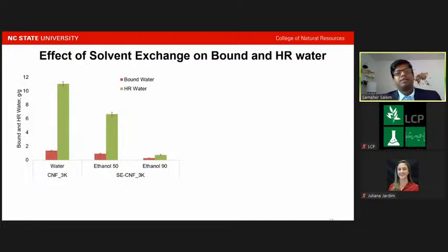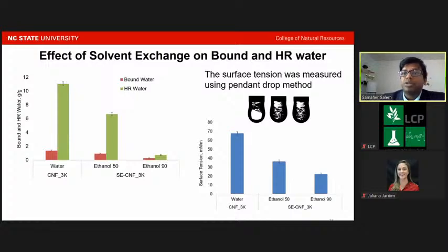Now, when we tried to find out how the solvent exchange method increases the reactivity, we measured the bound water and the hard to remove water content for the samples. And we could see that both the bound water and the hard to remove water decreased as the water amount in the sample decreased. That is, as we go from 100% water to 50% water to 10% water, the hard to remove water and bound water decreased much lower. And thus, it increased the reactivity. We also measured the surface tension using the pendant drop method. And we could find that there was a decrease in the surface tension due to the increase of the ethanol content, that is, the decrease in the water content.